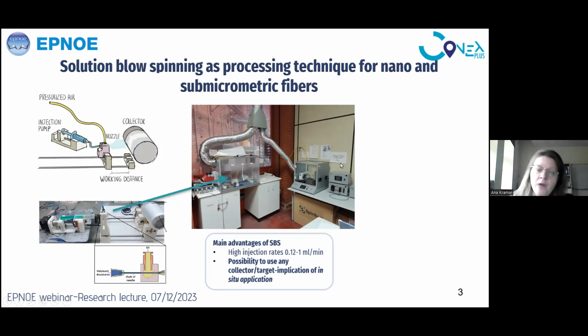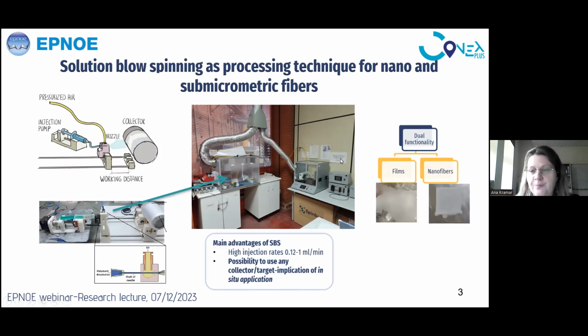So why would we use solution blow spinning instead of electrospinning? The first reason is that in solution blow spinning we can have high injection rates. We are able to process up to 1 milliliter per minute of polymeric solution. Since we don't have an electrical field and don't use electrical voltage, we can use any collector, and this implies in situ application. Another advantage is that solution blow spinning as a technique has a dual functionality. If we change the parameters of the spinning and of the polymer solution, we can get either nanofibers or films.